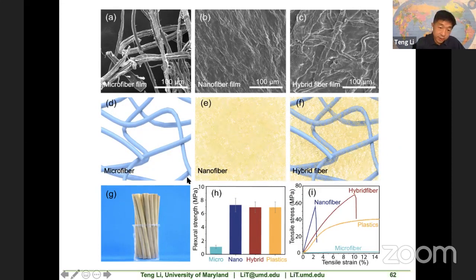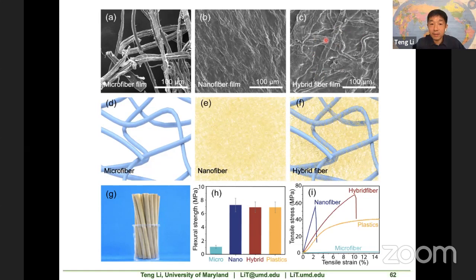Now, this here is a bunch of straws we made, and the length of the straw is around 10 centimeters. The diameter is a few millimeters up to 1 centimeter. Now, this is the SEM of the microfibers, and they are very loose, as you can see a lot of voids there. And this is the pure nanocellulose fiber film. And if we mix together, this is this one. I should use the laser pointer here. You can see that the nanofibers are really wrapping around the microfibers to form a very dense network.